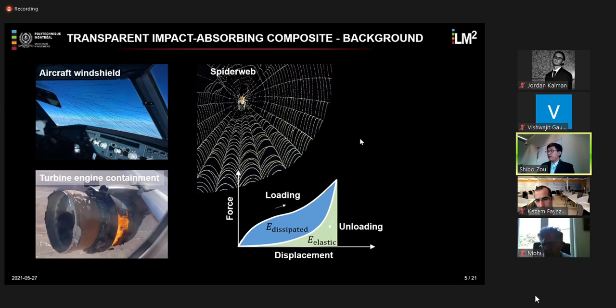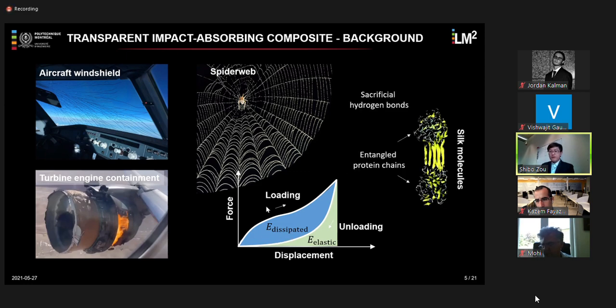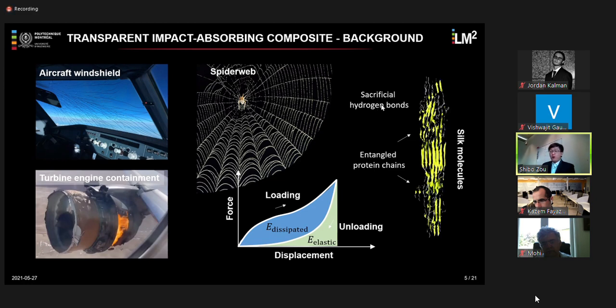And later research found that this high energy dissipation behavior in spider silk is attributed to the silk molecule structures. In the silk molecule, there exists a large amount of sacrificial hydrogen bonds within those entangled protein chains. Under stretching, those hydrogen bonds will be sacrificed, they will be broken, and release those entangled hidden chains that we call hidden lengths. And the breaking of the sacrificial hydrogen bonds and the unfolding of those entangled chains contribute to the high energy dissipation of spider silk.